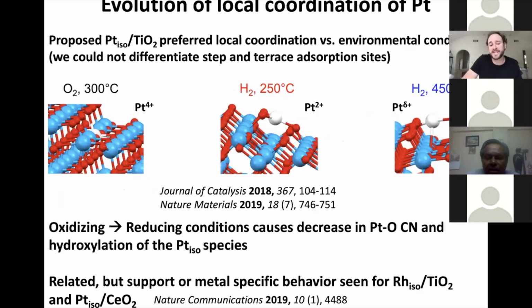And what we suggest is, as you move from oxidizing conditions to more reducing conditions, single platinum atoms, their local coordination will adapt. Under oxidizing conditions, platinum wants to dope into a cation vacancy and sit where titanium typically does. It makes 6 bonds to oxygens and some extended bonds to titanium. As you mildly reduce it, it wants to pop out of the surface and sit in a 2+ configuration. And as you reduce it even more harshly, it becomes hydroxylated and becomes mobile and moves around on the support.